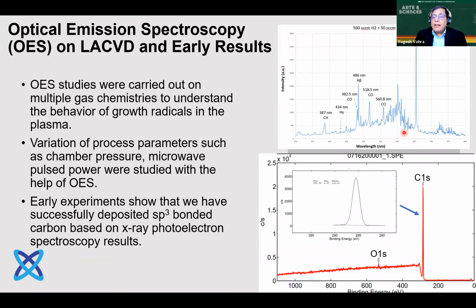You can see that with higher resolution than what the plasma emission spectroscopy shown here, you see a lot more details on different species, what you see here in the plasma, and you can get a lot of important diagnostics information for processing. And the bottom graph here is just some of the initial deposition showing carbon coatings in this large area CVD system.